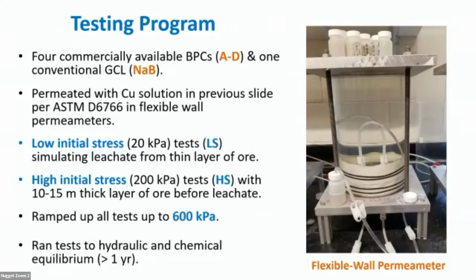We ran the tests under 2 different conditions. A low stress test, which is pretty typical in practice, it's conservative. And then a high stress test where we actually put a high load on the GCL first and then began to permeate it, simulating more like what we might see in the field, where we build a liner, we put the ore on top, and then we begin leaching it with that overburden pressure in place. And we ramped all the tests up to 600 kPa to simulate different ore thicknesses that we might run into in the field.